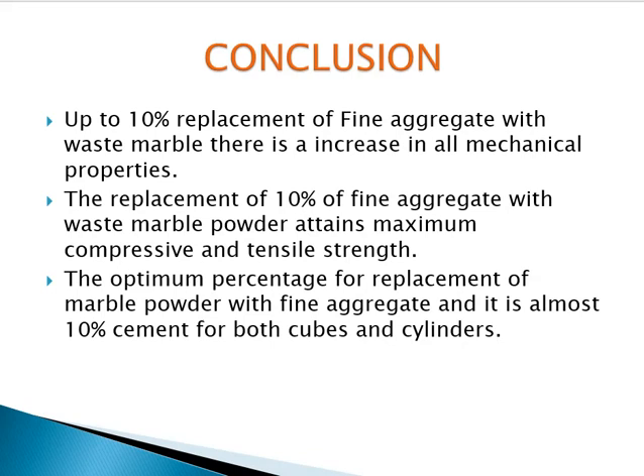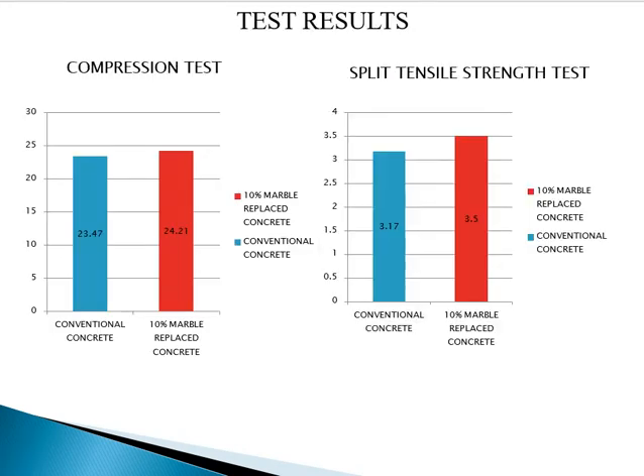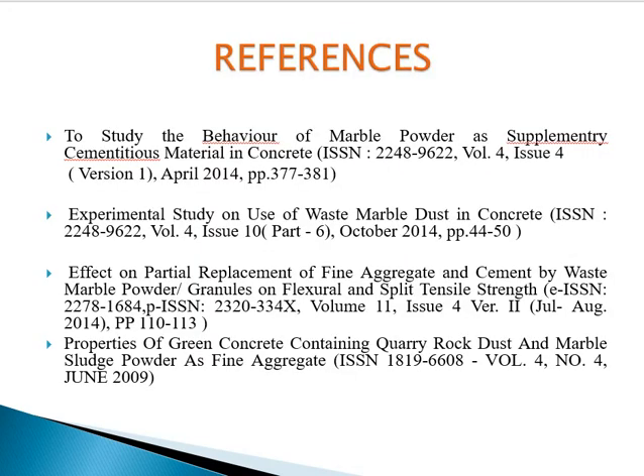Conclusion: Up to 10% replacement of fine aggregate with waste marble powder, there is an increase in all mechanical properties. The replacement of 10% of fine aggregate with waste marble powder attains maximum compressive and tensile strength. The optimum percentage for replacement of marble powder with fine aggregate is 10% for both cubes and cylinders. These are the test results compared for compression and tensile strength. These are the references taken from other journals. Thank you.